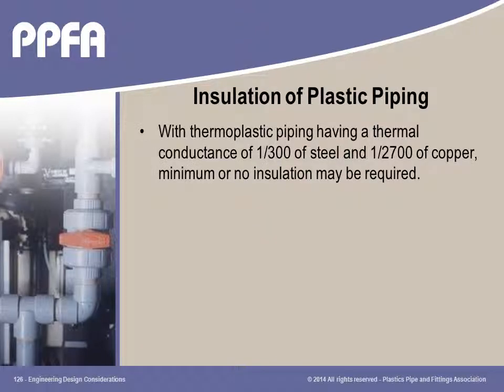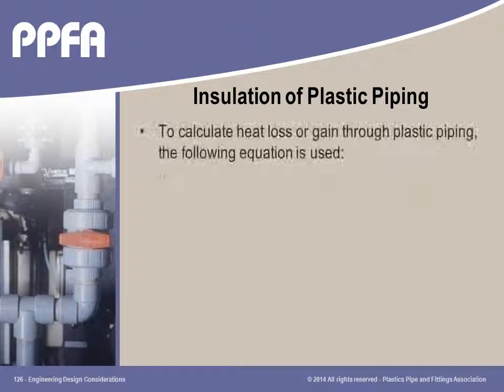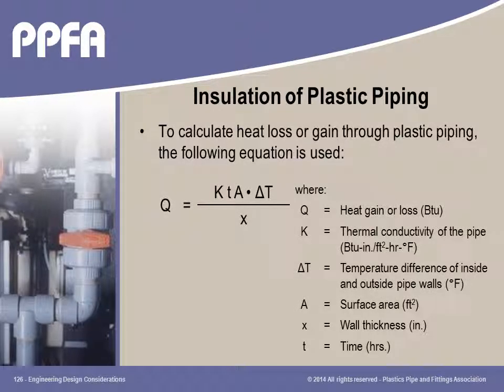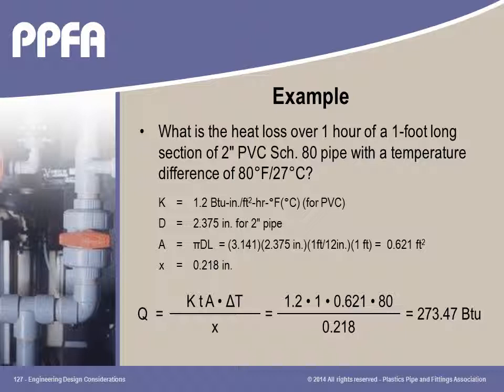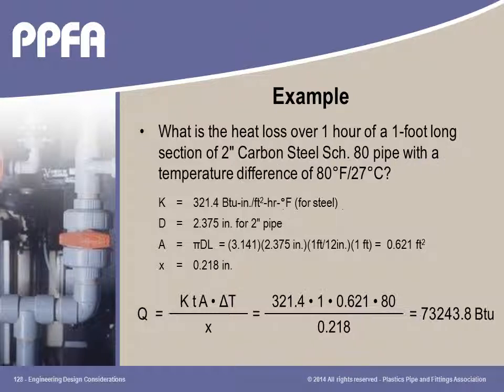Heat loss in metal piping is about 200 to 300 times greater than that of plastic. Therefore, plastic piping requires less insulation than metal piping systems. To calculate the heat losses of any piping material, use the listed equation. In the example, PVC had a heat loss of 273.5 BTUs. With similar conditions of service and pipe diameter using steel pipe, the heat loss of 73,243.8 BTUs is almost 268 times as much as PVC.